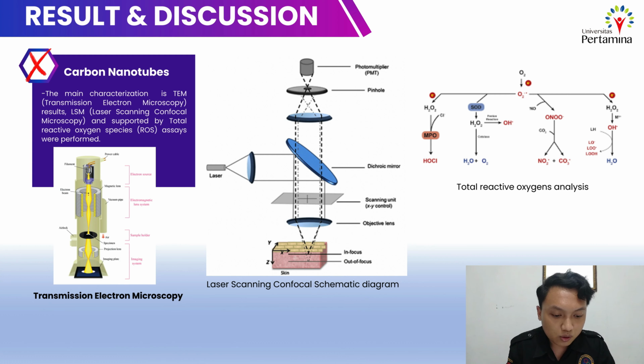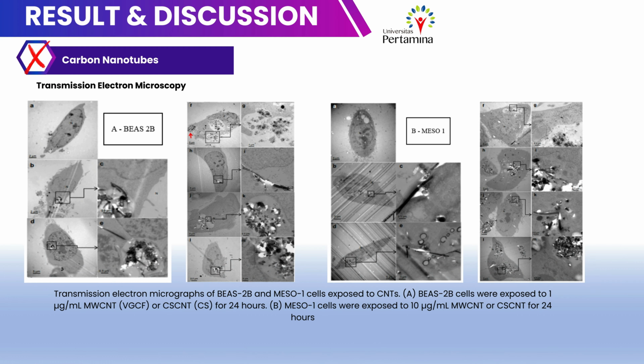When compared to carbon nanotube, which has the main characterization of thin-section transmission electron microscopy, which is used to visualize the interaction between carbon nanotubes with BEAS-2B and MSTO-211H cells after exposure for 24 hours. The results show no overlap in the signal of early endosome and CRT in the cytoplasm of BEAS-2B and MSTO cells. The lysosomal distribution of VGCF and VGCF aggregates was more clearly seen in figure 2A, B. Two holes were observed in the process of VGCF aggregate, figure 2G.